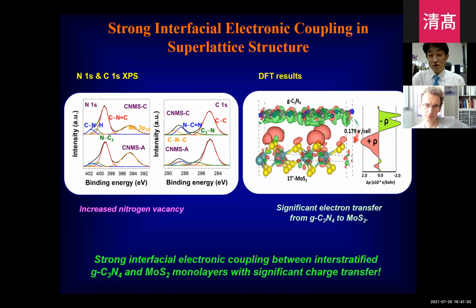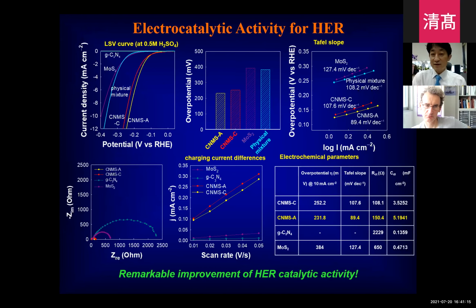Also, from the DFT calculation, we confirm the occurrence of distinct interfacial electron transfer from the carbon nitride to the MoS2 layers. We applied those materials as an HER electrocatalyst, as you can see here. Compared with the pristine MoS2, the resulting nanohybrid shows much better electrocatalytic activity for the HER reaction. Improvement of the reaction kinetics is confirmed by Tafel slope calculation. Also from the impedance analysis, charge transfer kinetics can be remarkably improved by the hybridization.